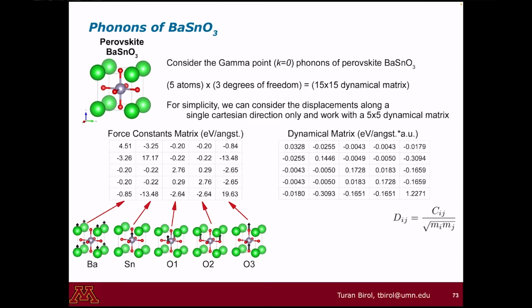They either displace atoms one by one, which is called the frozen phonons approach, and calculate the forces, or they might be doing DFT. But most DFT codes do this in a way blind to the symmetry of the system. Not all, and sometimes symmetry is used to some extent. So if you're a developer, please don't get offended. I'm making an overgeneralization here.